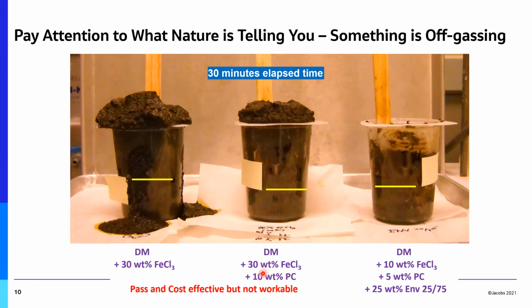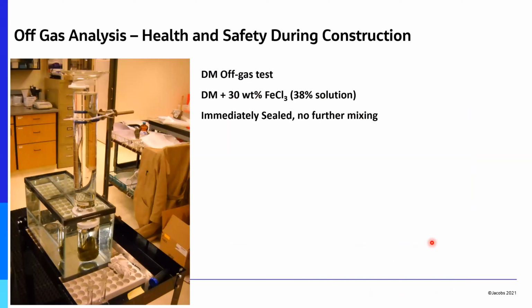Because it was so cost effective, we then looked at it with the Portland cement. That was still swelling to about 3 times its initial volume. And so that was rendered not workable either, right? Because how are you going to get this stuff off site? This was like a mousse. You couldn't handle it. By the time we actually got it to be a solidified material that was workable, we broke the bank on exceeding the number of reagents we had to use. So this got kicked out, even though it was the most cost-effective one there, but it wasn't workable.